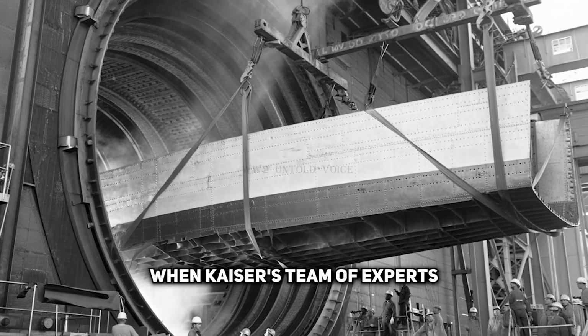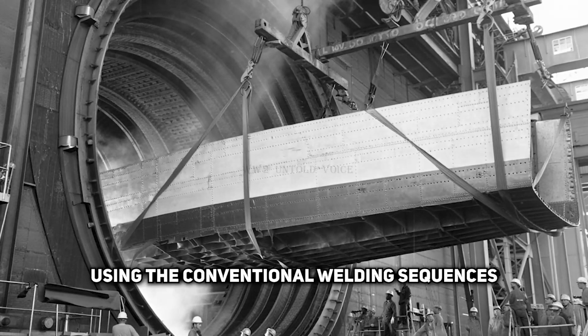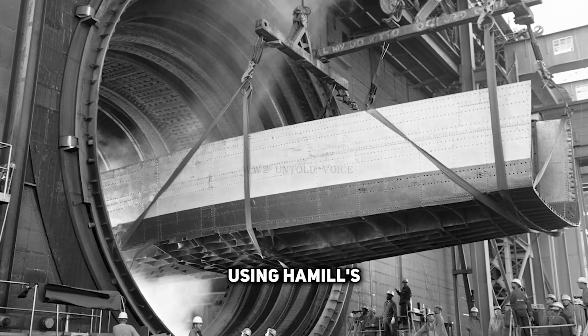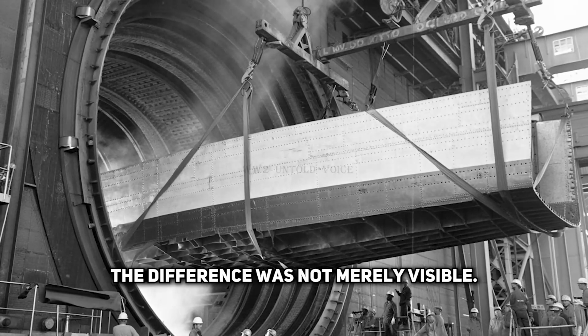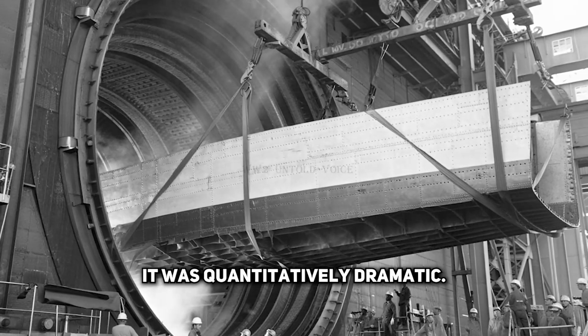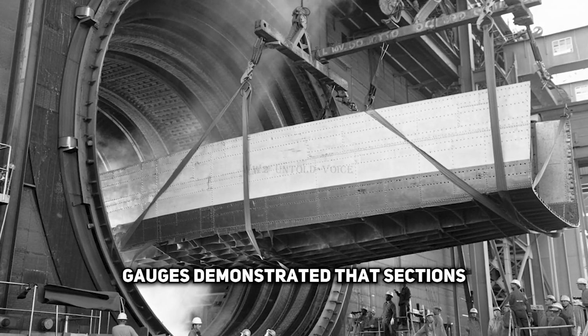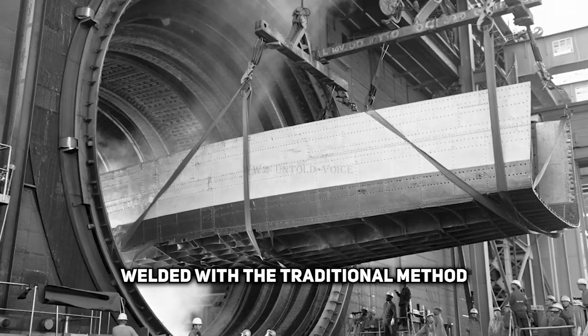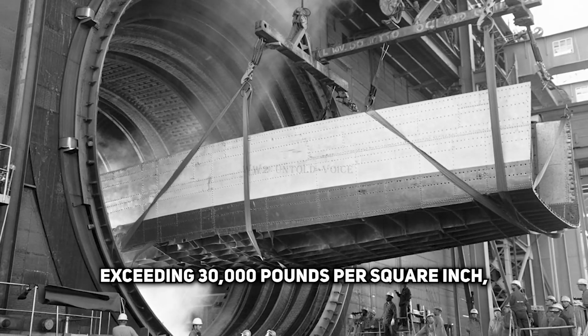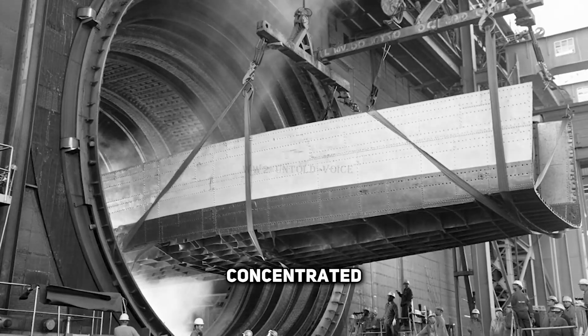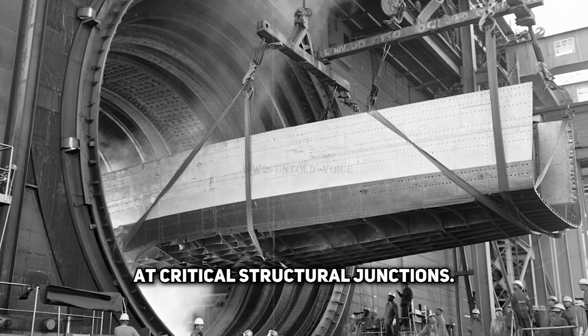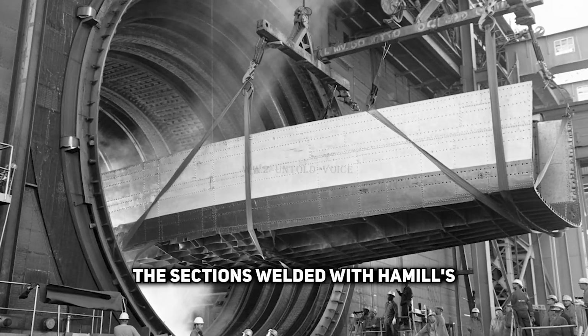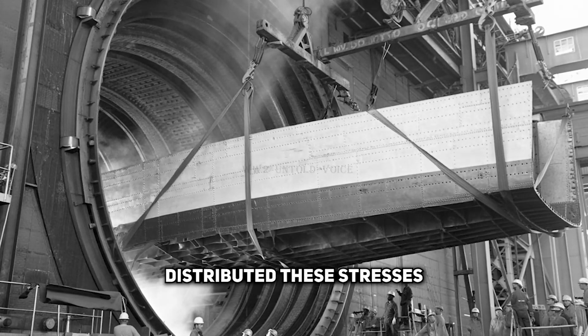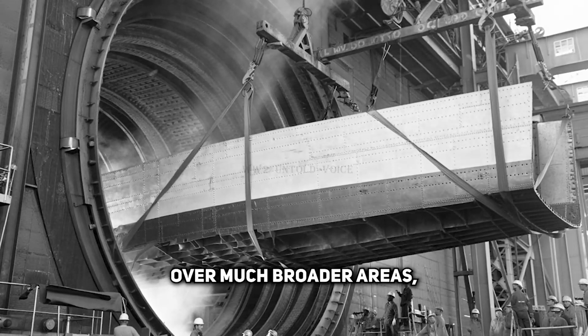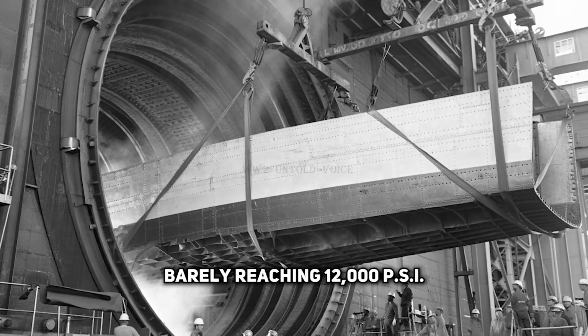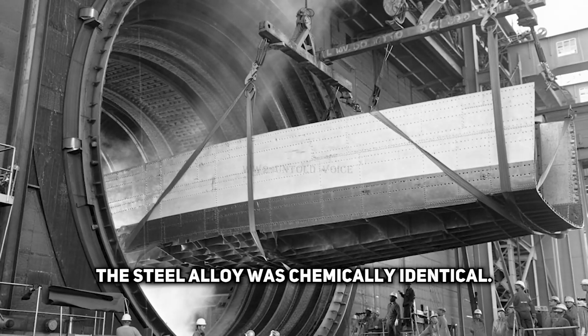When Kaiser's team of experts compared hull sections constructed using the conventional welding sequences against those built using Hamill's methodical approach, the difference was not merely visible. It was quantitatively dramatic. Sophisticated residual stress gauges demonstrated that sections welded with the traditional method carried internal tensions exceeding 30,000 pounds per square inch, concentrated at critical structural junctions. In stark contrast, the sections welded with Hamill's sequenced approach distributed these stresses over much broader areas, with peak readings barely reaching 12,000 psi.